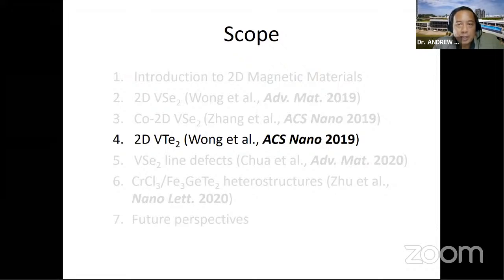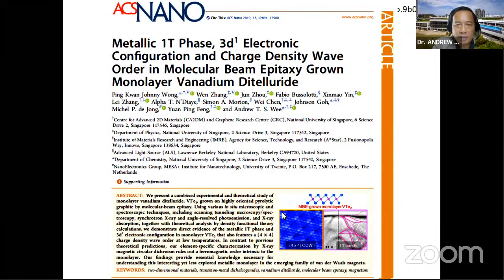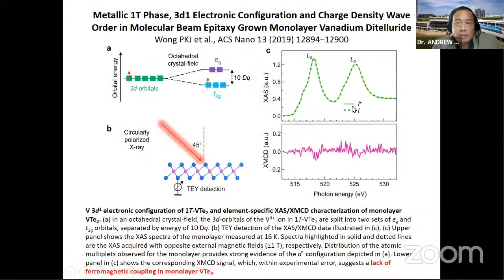So we did the same thing. This is monolayer vanadium ditelluride. And again, in the XMCD signal, you can see the difference between the left circularly and right circularly polarized light. The difference is almost zero. So again, we can see no evidence for intrinsic magnetism in this vanadium ditelluride.